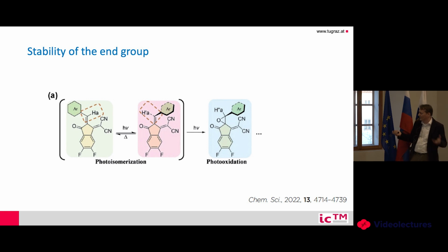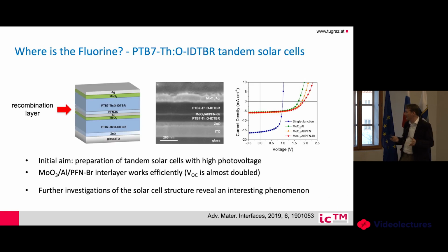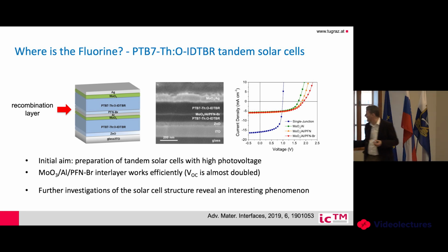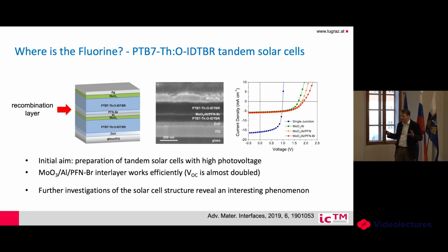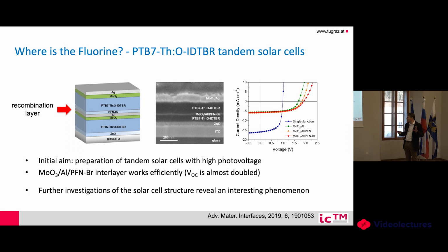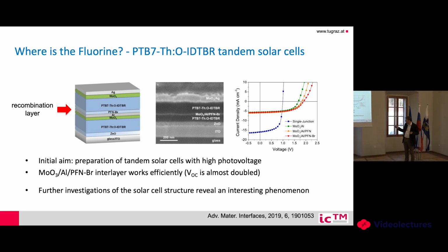So the problem is really to go, and this is good for me as chemist, to find structures where you can block this rotation and where you can block this photoreaction. Yeah. However, there are some other issues which I also show you from our own research. Actually, you see these fluorine groups here in organic solar cells. So we have a lot of fluorinated compounds at the moment. The state of the art materials always contain fluorine atoms.